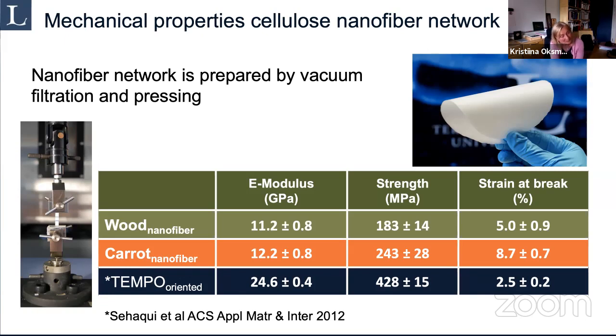But then I found a work made by Hossein Sehaqui, and he used TEMPO oxidized nanofibers, and he made a cold drawing of the nanofiber network when it was wet, and he managed to get a draw ratio of 1.6 and managed to get an actually oriented network. And you can see that the properties are double those of our carrot nanofiber network when it's slightly oriented. So of course it would be really nice to use these networks in composites, and there is also work done where people have impregnated these nanopapers with resin and got very high mechanical properties.